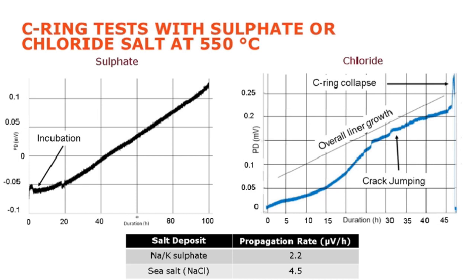If we have a look at the chloride salt, we see something similar, except we've not got that incubation time. We do have an overall linear growth rate. There's a little bit of jumping we can perhaps see going on there. But I think the key thing to note here is that with these two salts, we see a very different rate of propagation. So obviously these aren't calibrated. We've just got potential difference here, but it does correspond to the crack size.